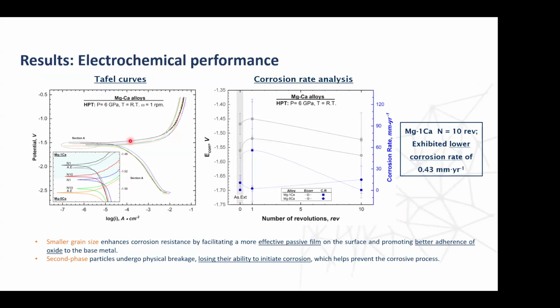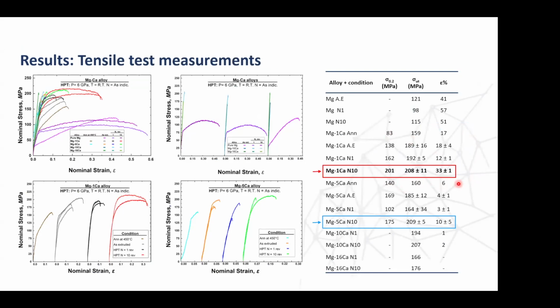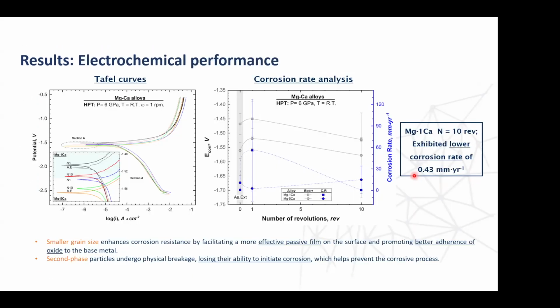These are the Tafel curves from the linear sweep voltammetry. And if you get this kind of curve, if you are familiar with corrosion, then the balance between anodic and cathodic reaction will give the actual corrosion voltage, and from the specific corrosion voltage we can calculate the corrosion rate. So we did get the lowest corrosion rate of 0.43 millimeters per year in magnesium 1 calcium 10 turns, and this, as you saw before, is one of the best in terms of mechanical behavior. So very promising. This is one of the lowest values when we looked at the literature.